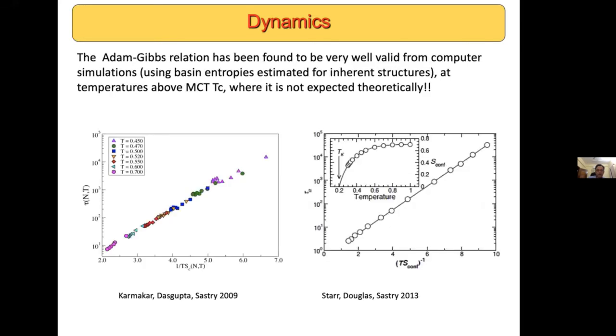Okay, now what's the situation with respect to the observed validity of this relation? So what has been seen in a variety of computer simulations, typically always carried out at temperatures above the mode coupling Tc or the dynamical transition temperature, is that the Adam-Gibbs relation works rather well. But the problem is it works rather well, and these are two examples from our own work.